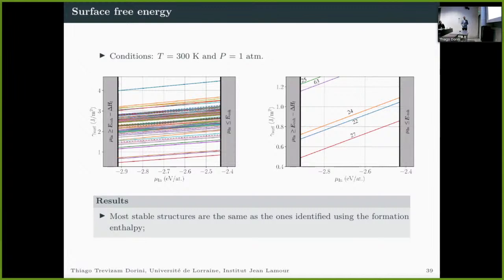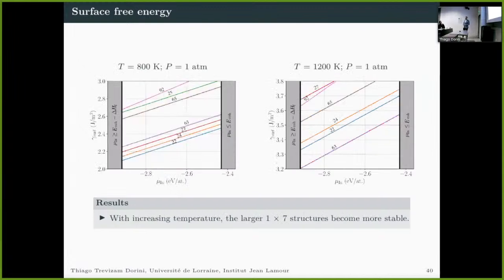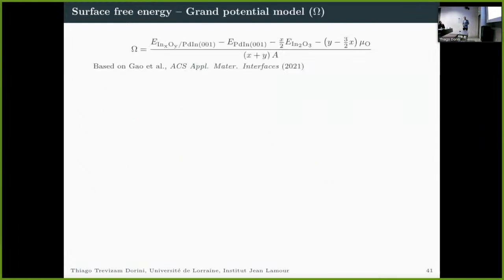and 63. When you increase the temperature on this model, there is an interesting shift where some of the bigger structures, the 1x7 structures, start to become more stable than the smaller 1x3 structures. As we see at 1200 Kelvin, we have structure 63 being the most stable of all the other structures.